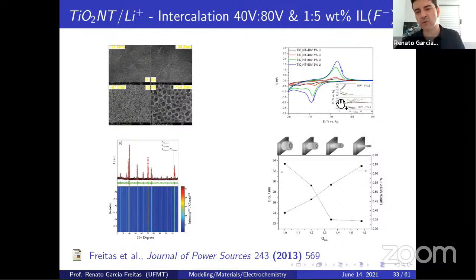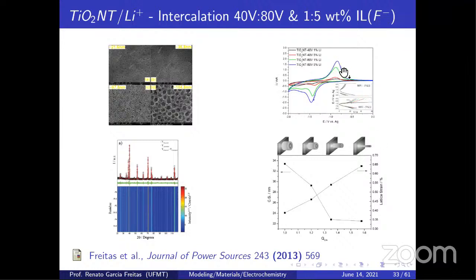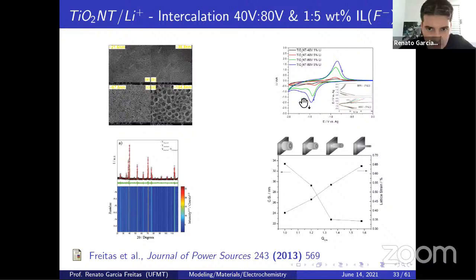10⁻⁴ millivolts per second, the voltammetry, and we observe the oxidation, reduction of lithium, the charge, discharge of this part here as well. And we constructed this plot, which we observe here. We have anodic charge, and down there, the cathodic charge, isn't it? So we have a very reversible system, like here, anodic divided by cathodic equals 1, when we have the crystal size like this value, 34, obtained by Rietveld refinement. So 34 nanometers leads us to this part here, which is small lattice strain, which is the nanotube considered here.